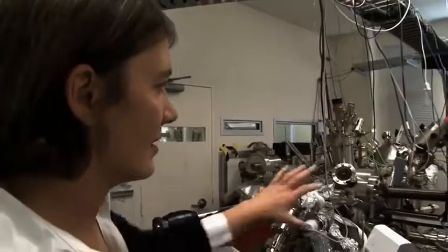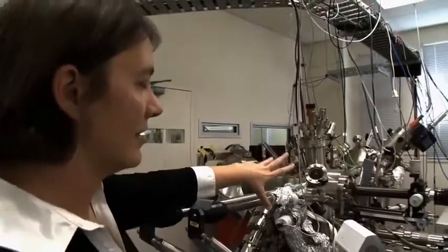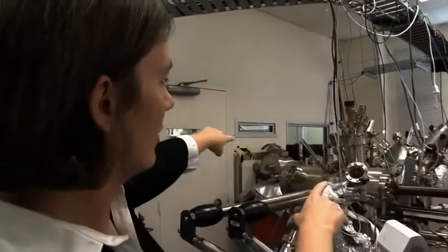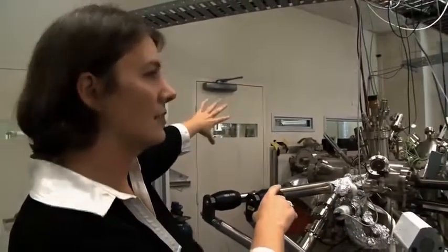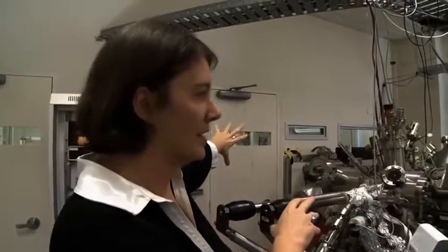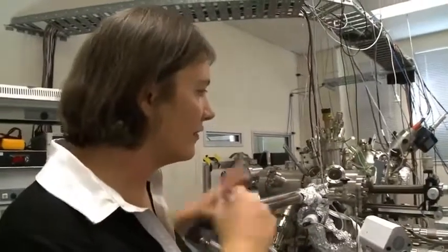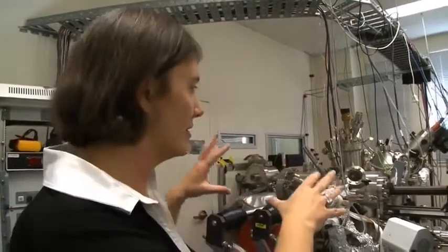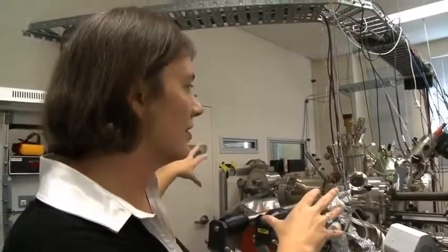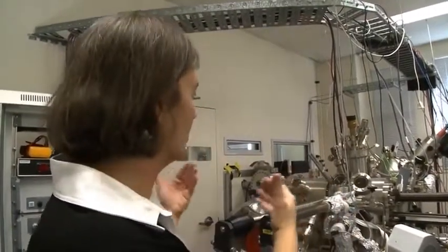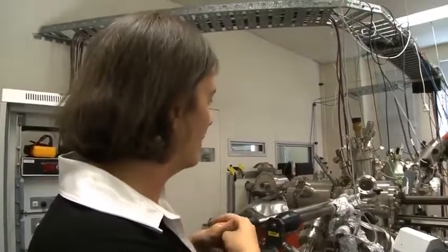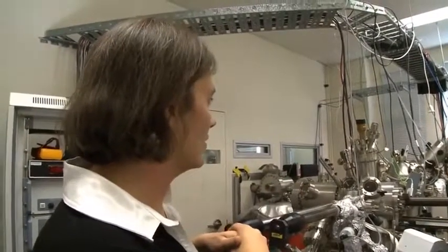So here, this is our scanning tunneling microscope on the right-hand side here. And this is connected under ultra-high vacuum with a piece of stainless steel to a molecular beam epitaxy system. Several groups have tried to connect these two technologies before, and they found that the vibrations from the crystal growth side actually destroyed the imaging that you would get with the STM. So it's actually very difficult to bring those two technologies together. So we literally had to work with lots of engineers from both of the companies and independent acoustic engineers to bring the two technologies together.